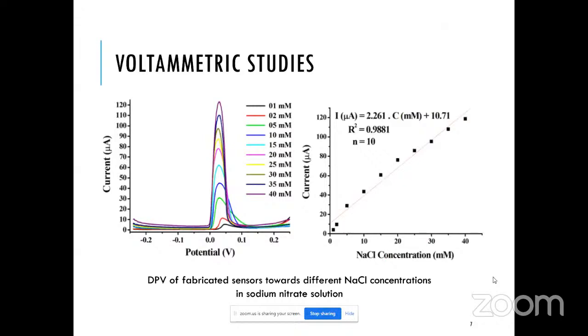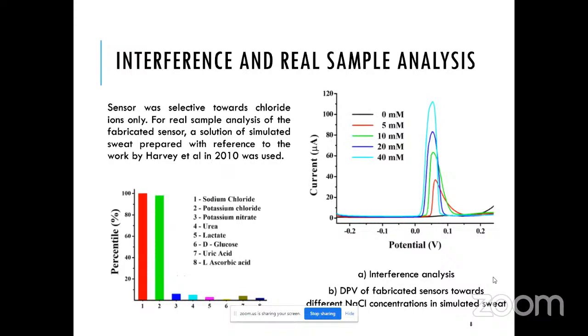For quantification of the response, the technique called differential pulse voltammetry is utilized, and we can see that a linear response was observed for a range up to 40 millimolar. Then the electrode was tested for interference and real sample analysis. It can be seen that even in the presence of common interfering molecules, the synthesized catalyst was selective only towards the chloride ions. It was also tested with simulated sweat sample prepared in reference to the work by Harvey et al. And this proves as a proof of concept that the real-time application of the sensor is possible.